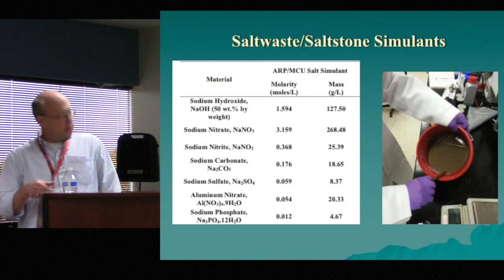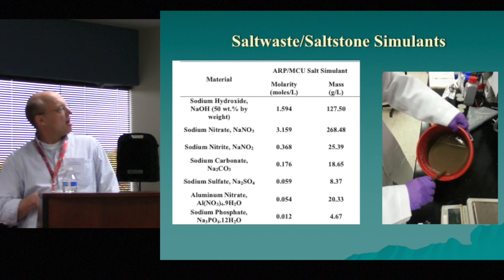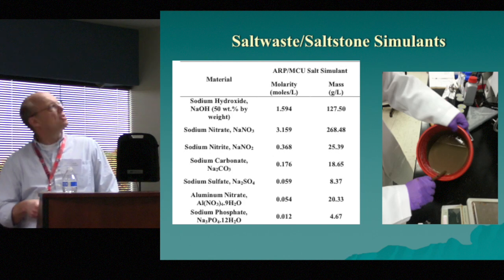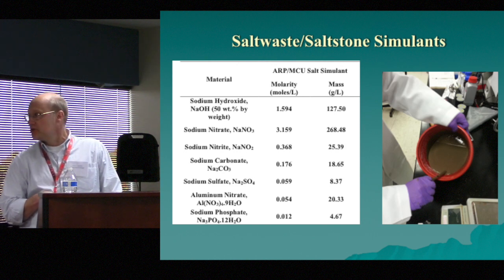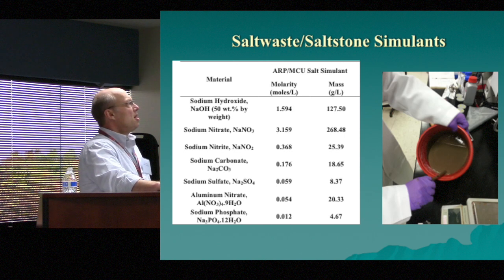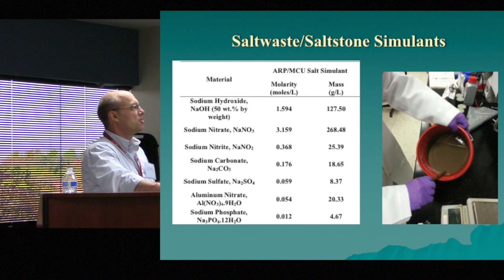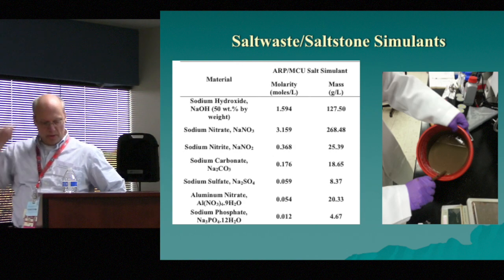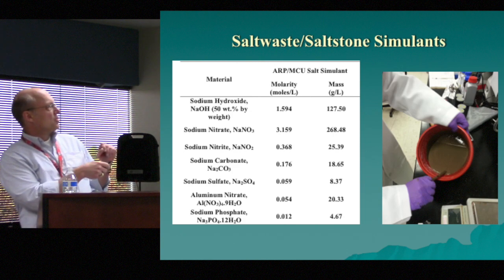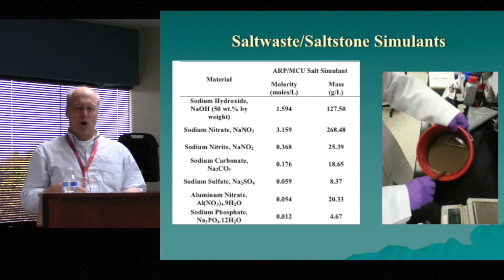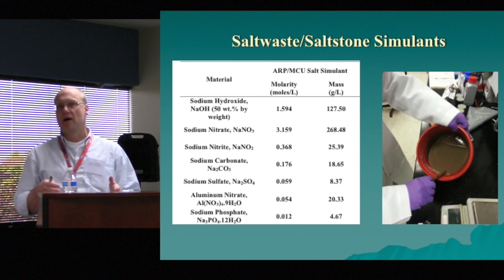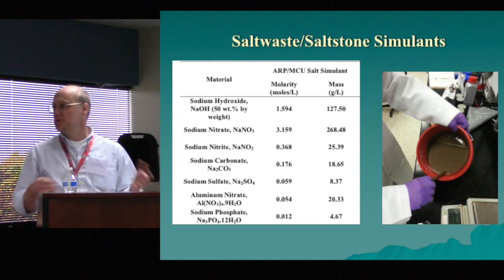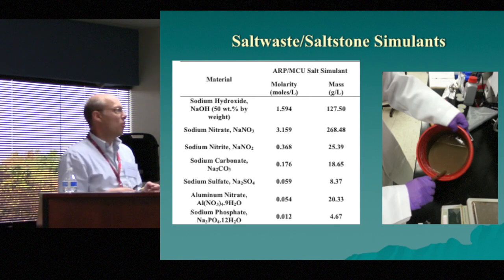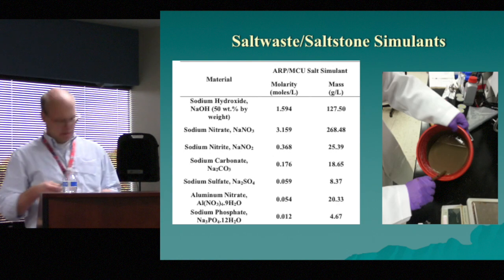So this is actually the simulant chemistry, and here it's a 0.6 to 1 ratio of wet to solid material, and this is what it looks like when you first mix this material up. If you look at the chemistry though, it is very high in nitrate, high in nitrite. It's got quite a bit of carbonate in it, also quite a bit of sulfate and quite a bit of aluminum. The important part about this, though, is that these, especially the sulfate and aluminum, are all constituents that can have a significant impact on how cements cure and their final properties. And we also use these often as actual additives for developing various properties in cement materials. Next slide.